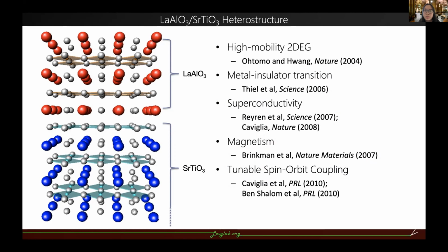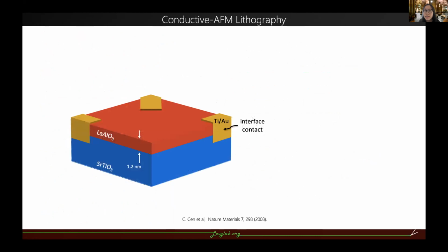And with the metal-insulator transition, our group has developed a technique called conductive AFM lithography at the LAO-STO interface, which can be used to pattern nanostructures such as nanowires and tunneling barriers at the interface. To do that, we start from the 3-unit cell LAO on STO substrate, which is insulating but highly tunable, and the titanium and gold are here acting as the interface contact.